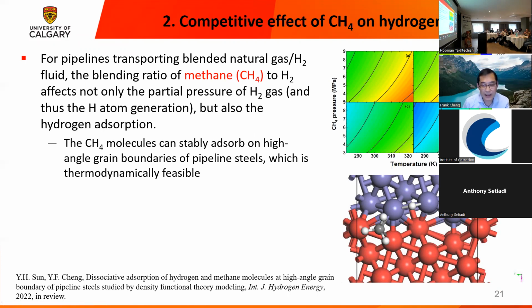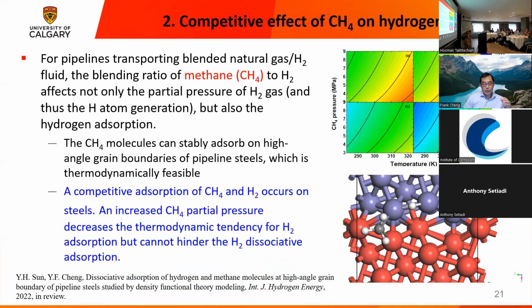So if the CH4 and the H2 co-adsorb on the steel surface, there is a competition of the two gas molecules. So that's why, if the CH4, the methane partial pressure, goes up, it can decrease the possibility of hydrogen embrittlement. Because what? Because the two gas molecules will compete with each other in terms of the adsorption on the steel surface. So from the hydrogen embrittlement perspective, when we increase the partial pressure of the methane molecule, the hydrogen embrittlement possibility will go down. So this is a direct answer from the thermodynamic analysis.